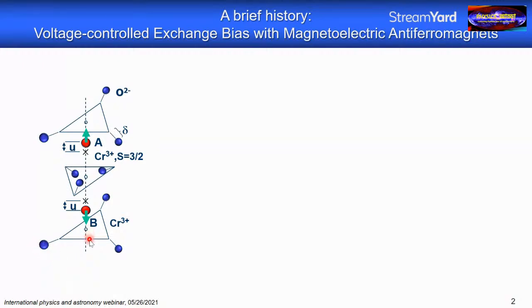And to keep it simple, the electric field here is applied along the easy axis. Now, in that case, charged particles do what charged particles do in an electric field. They experience a force and start to move into a new equilibrium position, and that's what's happening here. The chromium 3+ ions move along this axis and move towards this oxygen 2- triangles.